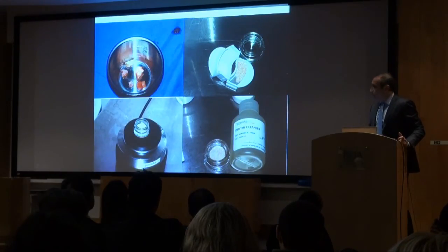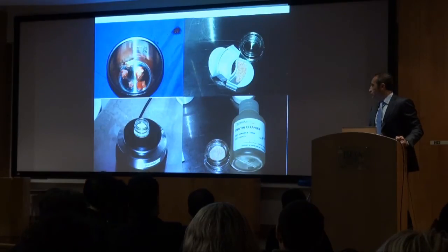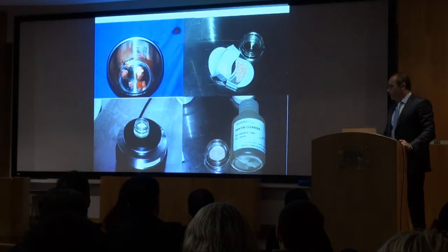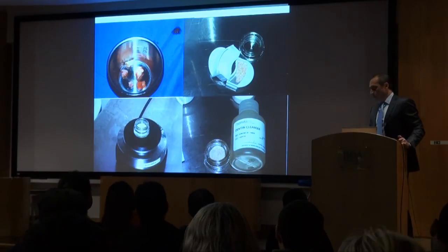You can do it or not, it doesn't matter, but for storage, we absolutely recommend heating it for 5 minutes at 150 degrees Celsius, just to evaporate all the liquids, to dry the dentin, and give it to the patient to keep for years.